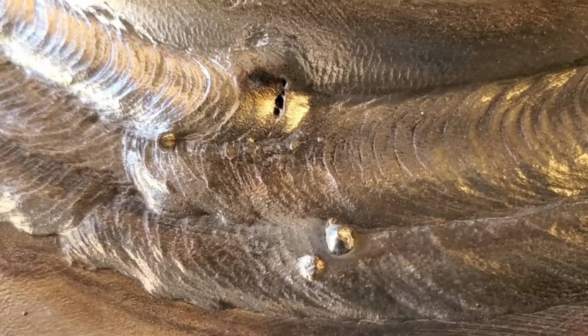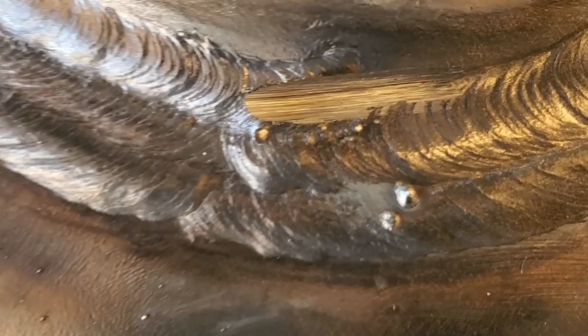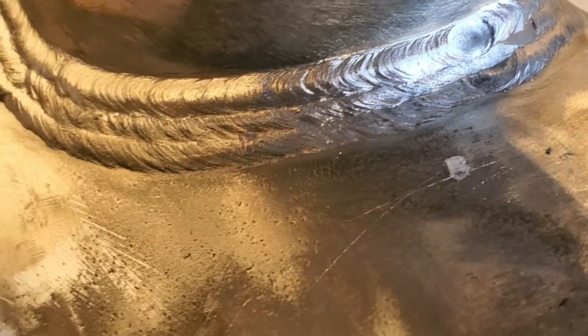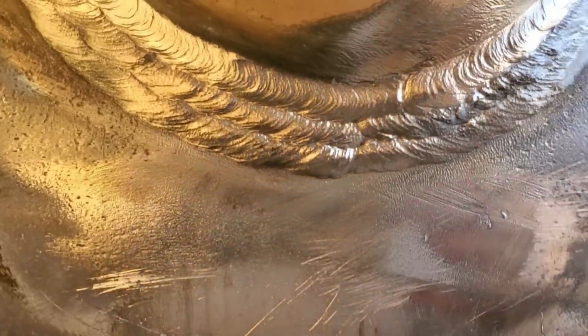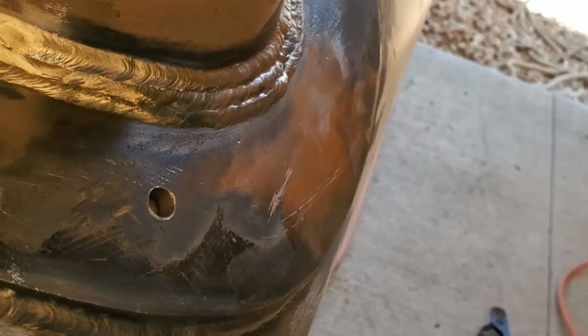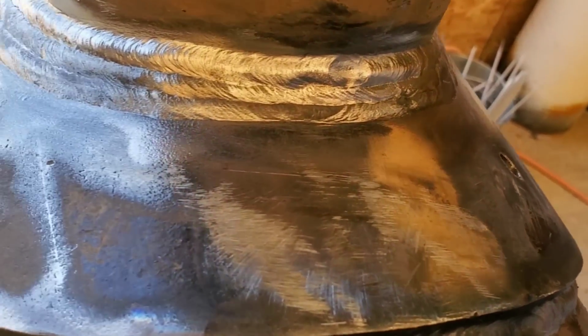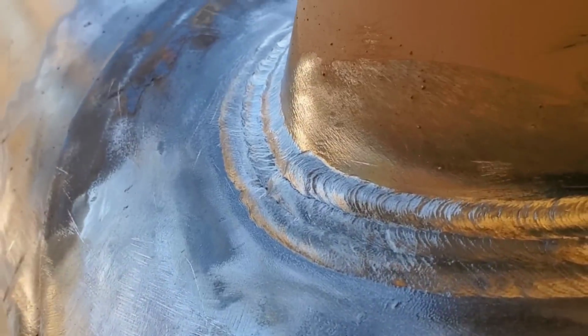Right here I had a little bit of porosity on my very top pass, so I had to grind it out. I don't need any kind of chance of failing the test that they'll be doing next, which is a dye penetrant test. When they do the dye penetrant test, they're basically checking for any kind of porosity that you left behind. If you have undercut or porosity, it will show in the dye penetrant test.